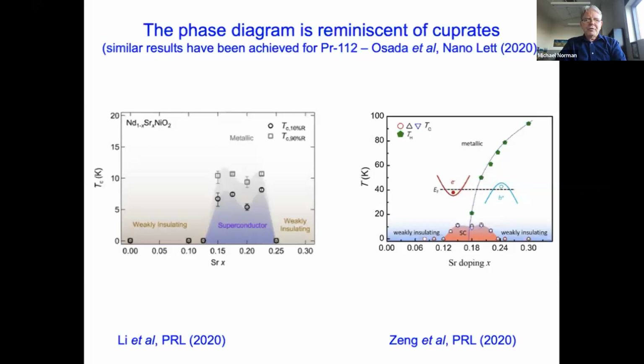The deal, of course, is on the underdoped side, you get something that's sort of weakly insulating. You don't see any real evidence for Mott insulator formation like you do in cuprates. And then you typically get weak insulating behavior on the overdoped side, unlike cuprates, where you typically get a pretty good metallic state.